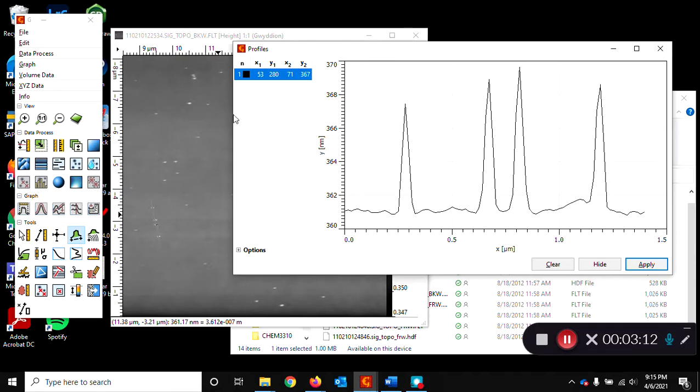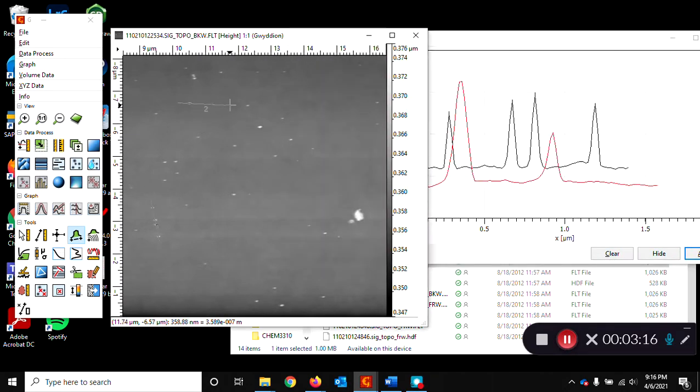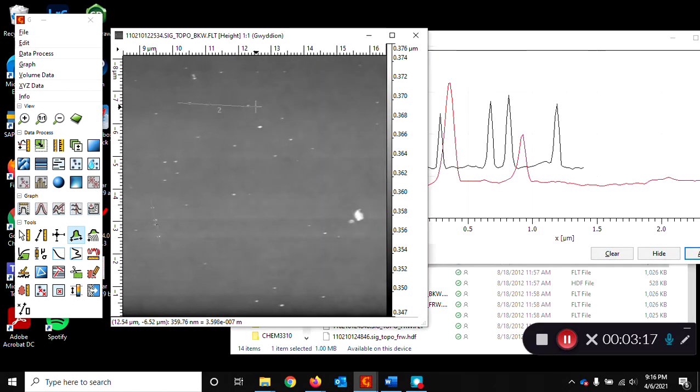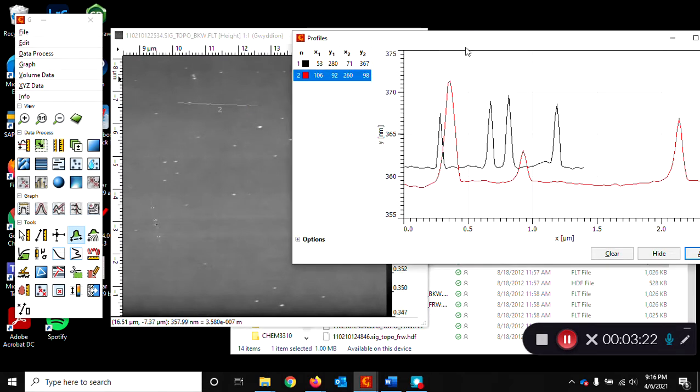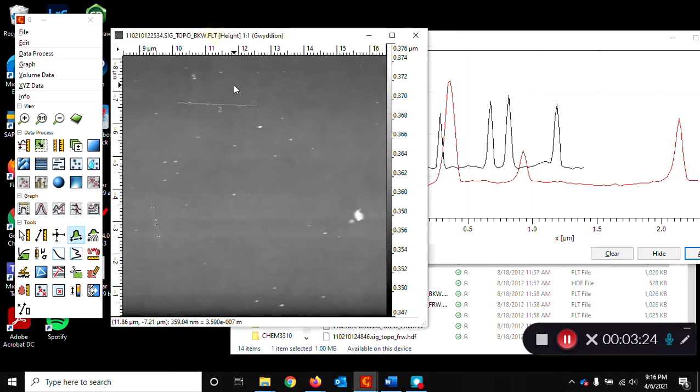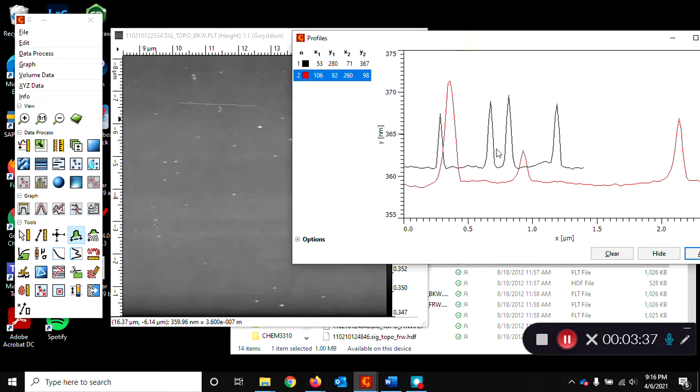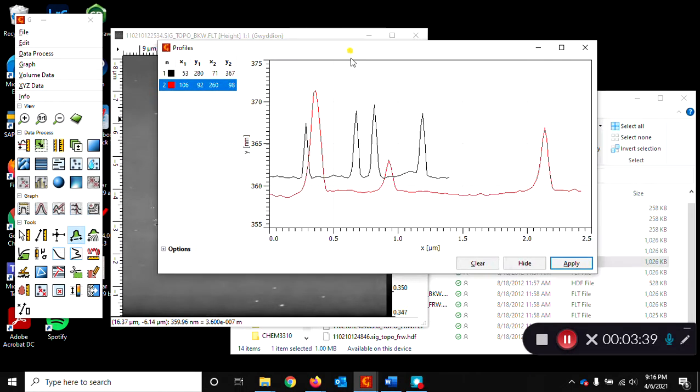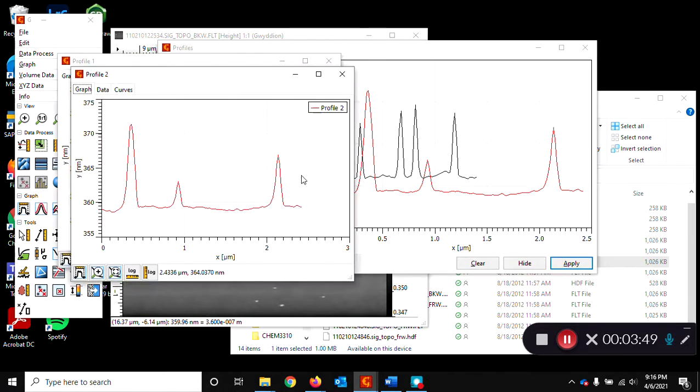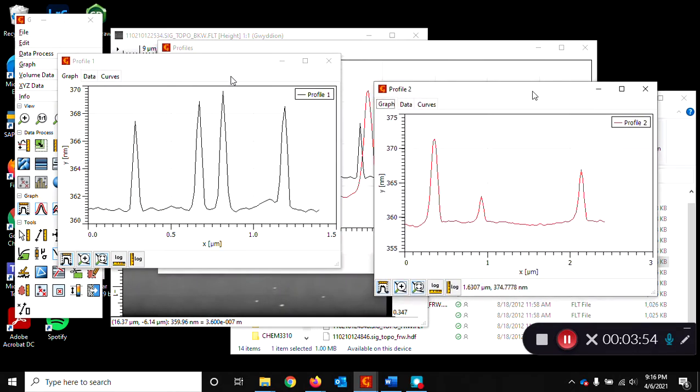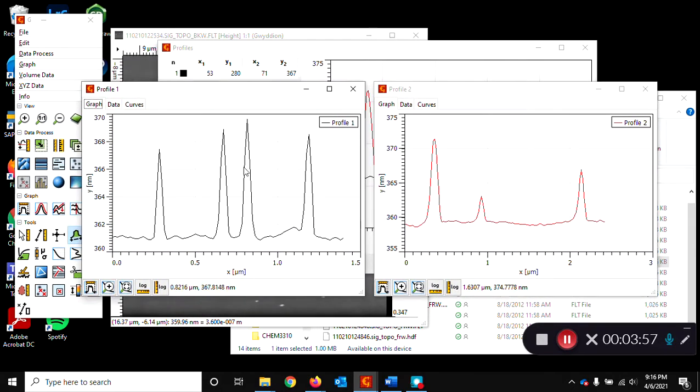So you can draw multiple lines and the computer will assign different numbers and colors to each line. And you want to try to measure 20 to 40 of these spots total in your sample to get a distribution of the particle size. So here you can see my two lines are overlaid. I can show them as separate lines. So when I apply I extract those profiles into a new data file and I set to separate them so I can measure without getting confused about what I'm measuring.